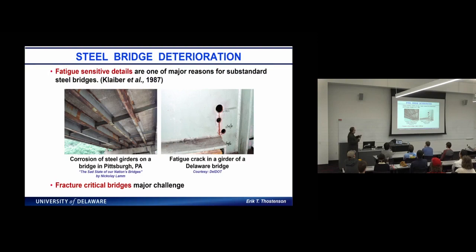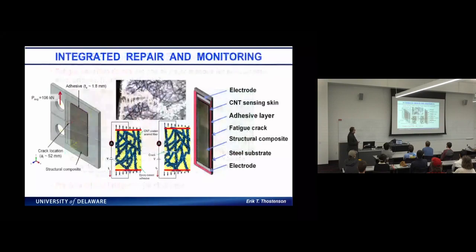We could bond a composite and design a composite system that would, we can clean the corrosion off, but also rehabilitate that girder. So our idea was to integrate both the repair as well as monitoring. And what you see in this picture actually is our compact tension specimen, and where we've integrated a structural composite patch to share some of the stress or some of the load and take that stress off of the crack. And this is a micrograph and a little cartoon showing where we've integrated the sensor right at the bond between the structural reinforcement and the steel plate.